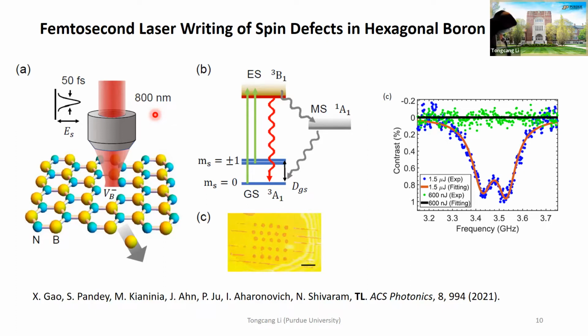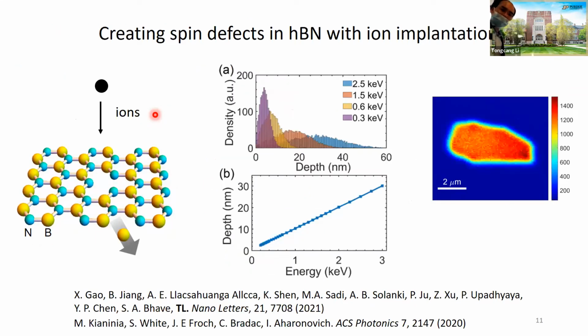We can control the density by the number of passes, but it is not accurate. The peak power is crucial to create this kind of defect. But once you fix the peak power for each single pass, then the more passes you put, the more vacancies you create. So it still depends on the resolution. We can create a cloud of defects with spatial resolution under 1 micron. So we want to go beyond that, and now talk about single layer, so now we want to reduce the thickness.